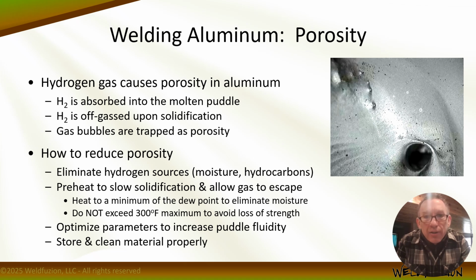One of the most common discontinuities associated with aluminum welding is porosity, which is directly related to shielding gas and the presence of hydrogen. Unlike steel, where hydrogen leads to cracking, here with aluminum it causes porosity. During welding, hydrogen is absorbed into the molten aluminum puddle because it has very high solubility. But upon solidification, the hydrogen is rejected or kicked out of the weld pool because it's no longer soluble, and that off-gassing can form gas pockets down in the weld pool, and rapid solidification can trap those pores before they have a chance to escape. And again, we often call that off-gassing, allowing the puddle time to off-gas.